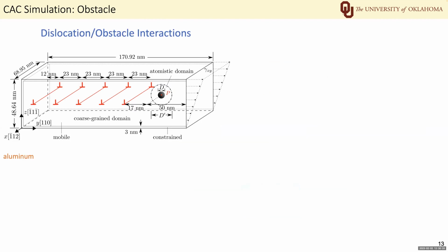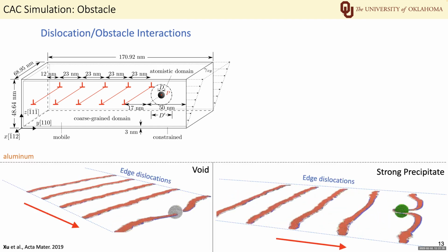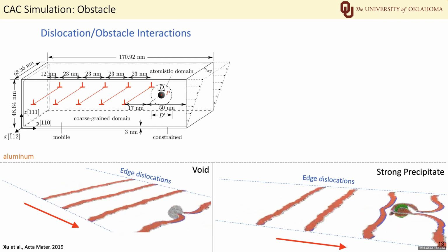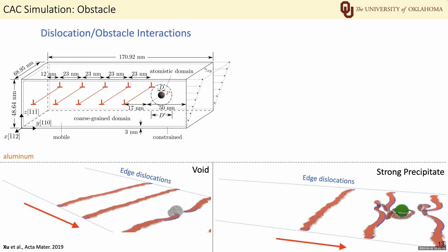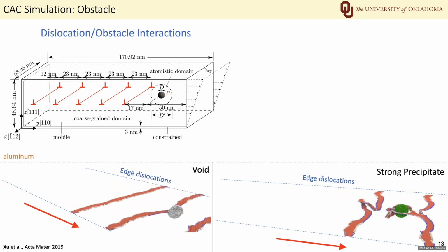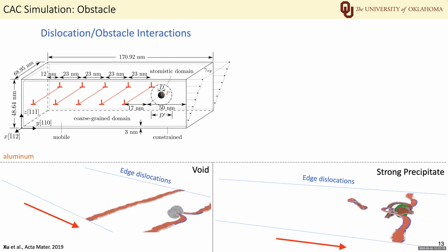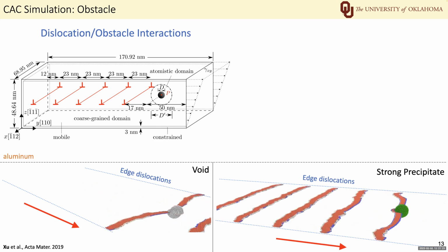The first example concerns the dislocation-obstacle interaction in aluminum. We aim to answer two questions. One, how does the interaction mode differ for different types of obstacles? And two, how does the interaction mode change with the number of dislocations? In the movie on the left, a series of edge dislocations sequentially shear a void. In the movie on the right, the void is replaced with a strong precipitate, and all these dislocations go around the precipitate instead of shearing it.